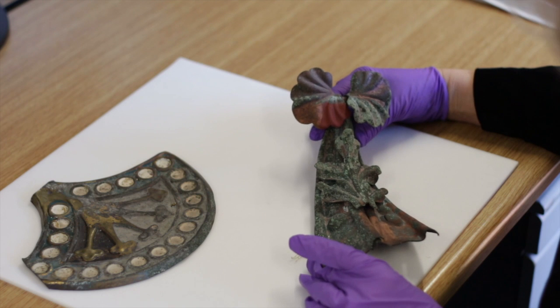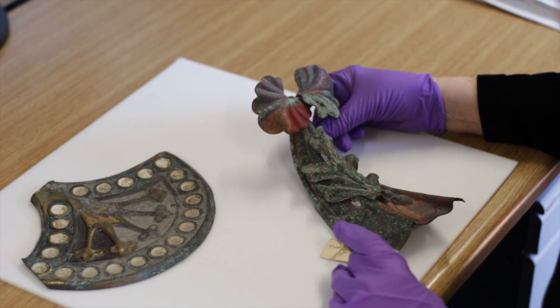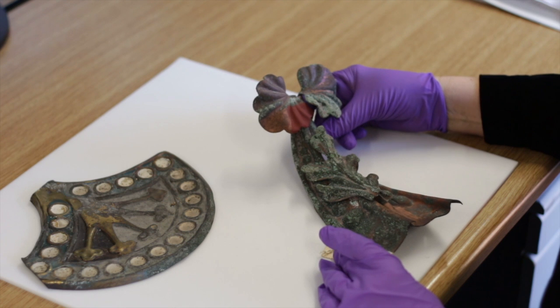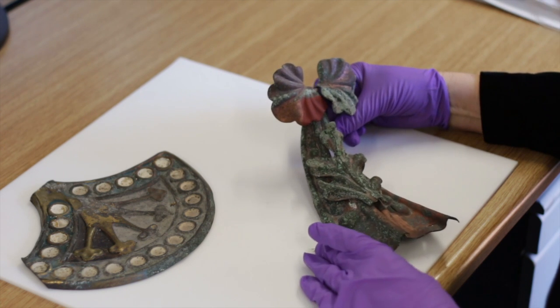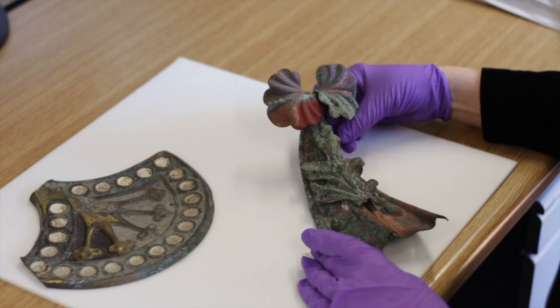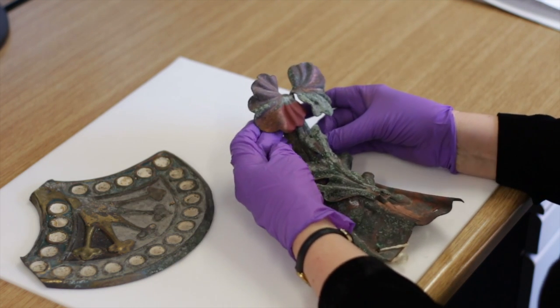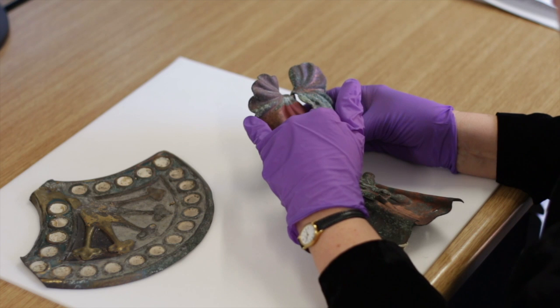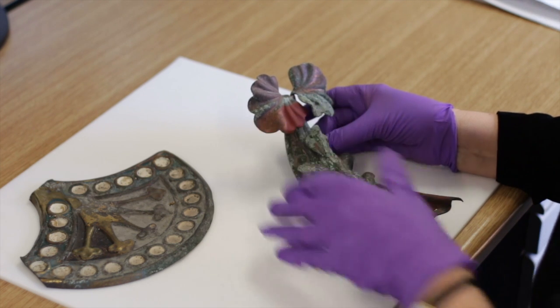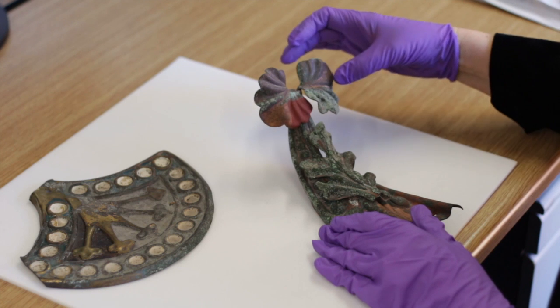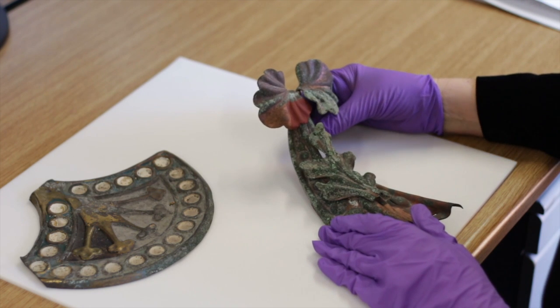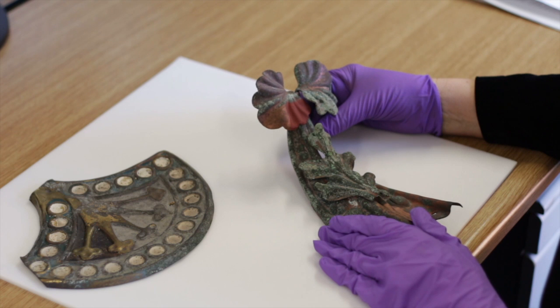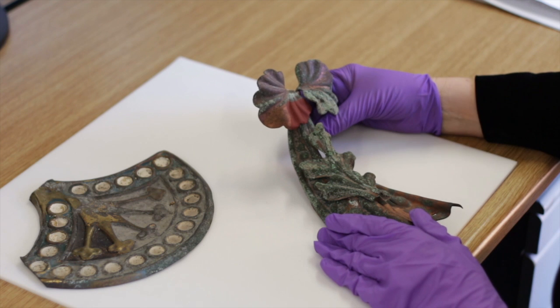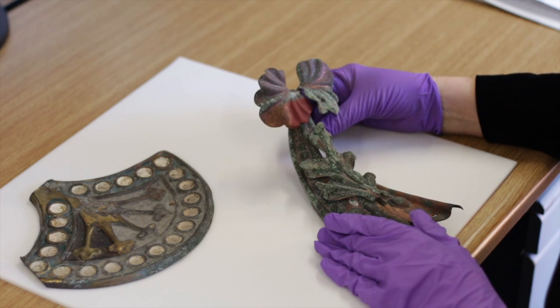So to that extent, abrasive cleaning methods, as gentle as possible, were implemented, just picking off the corrosion with brushes and little scrapers. Another method that was used, which was a pioneering method at the time, was to use a low-powered laser, and these areas here is where the laser was used. By directing the beam onto the corrosion products, it was possible to vaporize them, and it was a very effective and interesting method to use. However, it was time-consuming and therefore a pretty expensive way of undertaking the corrosion removal.